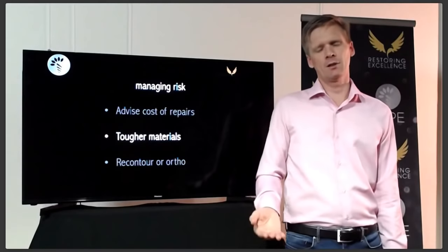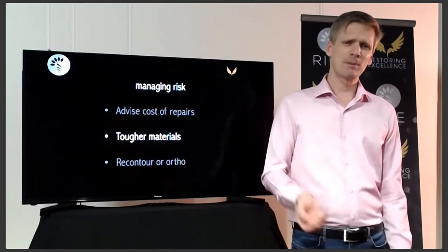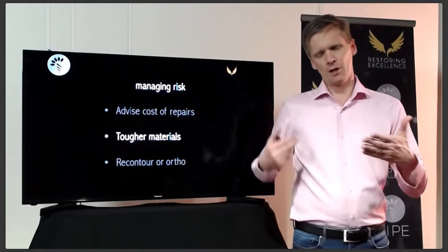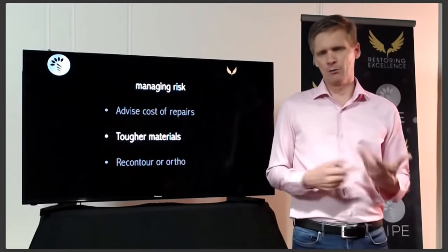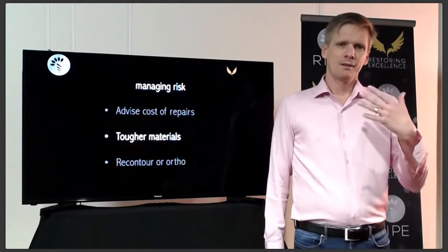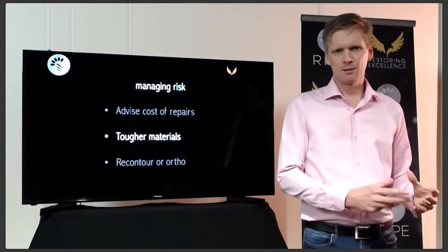Now, how thick does zirconia have to be to stop a fracture? It has to be about 1 millimetre thick. So for zirconia to resist fracture, it needs to be at least 1 millimetre thick. If it's less than that, then it will fracture quite easily. So that's the difference: zirconia might be stronger than Emax, but it's not tougher.